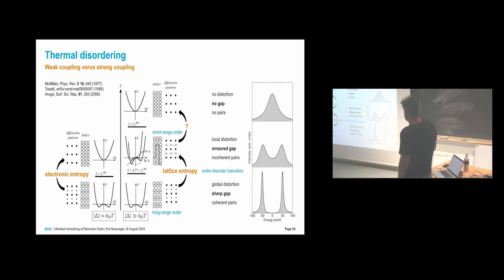metallic or insulating behavior. And this transition would evolve in a way, if you look at the gap: at low temperature you have a sharp gap, you have coherent pairs, electron-hole pairs, so to say, you have a global distortion. Here, in this scenario, you have broken up long-range phase coherence. You will smear your gap because you have local distortions. Your electron-hole pairs become incoherent, and then in the end, you don't have a gap anymore. So this is the cool thing. When we do ARPES, we can really look at the gap structure. We can see coherence in the form of sharp edges and peaks, and we can see incoherence in the form of broad peaks and smeared edges, filled-in gaps, and so forth.